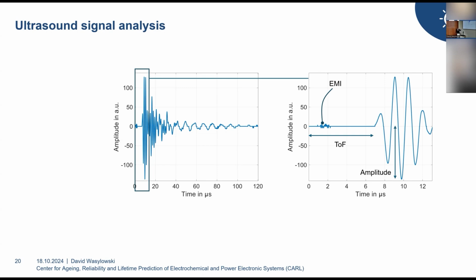So the first one is time of flight. This is just the time it takes for the sound to pass through the battery. Usually when we have a battery which is wider, the time of flight increases because the path just gets longer from the sending piezoelectric material to the receiving one. And then there is the second feature, the amplitude, also typically decreasing with wider cells, because the active material within the battery is actively dampening the sound wave, extracting energy from it.